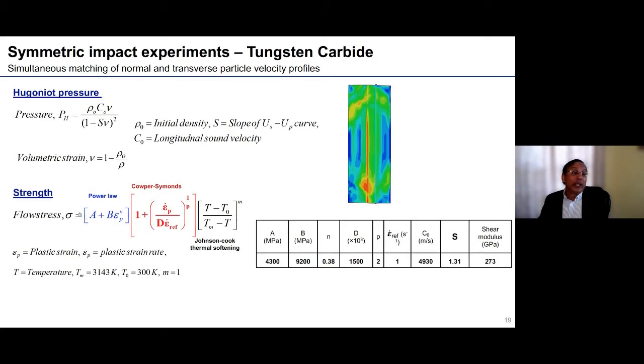So we use a power law for the tungsten carbide. So we do direct numerical simulations. This normal response is very well studied. And so for the strength of the tungsten carbide, we use a power law for the strain hardening, a Cowper-Symonds form for the strain rate hardening, and a Johnson-Cook kind of model for thermal softening. So here are shown the parameters. I'm not going to go into the details, which you can see in the papers.